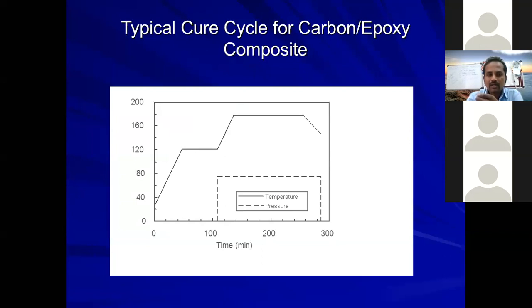So there is a ramp from about 35, 36 degrees Celsius to 120 degrees Celsius over 60 minutes, then again 100 minutes at 120 degrees Celsius, and again 155 degrees Celsius from 100 minutes to 250 minutes. Like this, up to 3 or 4 hours, the materials are cured at a certain temperature, depending upon the glass transition temperature of the materials.